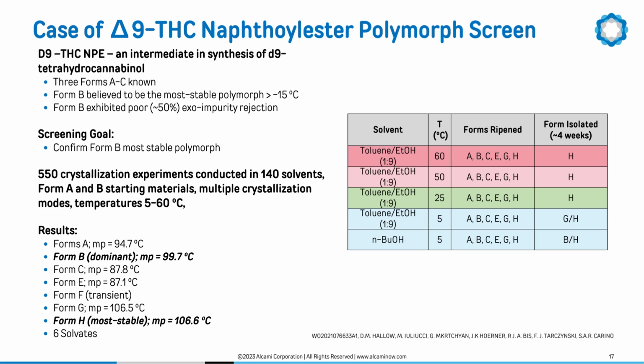A good example of a polymorph screen is one conducted on delta-9-THC naphthol ester, which is an intermediate used in the synthesis of the 9-THC. 3 non-solvated crystal forms were reported, forms A, B, and C, with form B believed as the most stable polymorph above -15°C. Crystallization process of form B was already in place, however it could not achieve satisfactory purification of form B from a stubborn impurity.